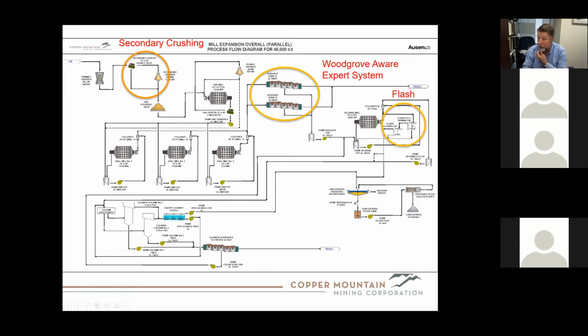We also added a flash flotation cell, which increased gold recoveries and also pulled out some of the coarser chalcopyrite, which allowed you to work a little harder elsewhere in the flotation system. Improved the bubbles in the cleaner tanks with slam jet spargers. And then the 3rd ball mill, as I mentioned, will be coming in. And currently we're in the process of putting direct flotation reactors in here, which is essentially, if my understanding is correct, flotation in basically in a vacuum, I think is what that is. But you'd have to ask someone else to clarify that.